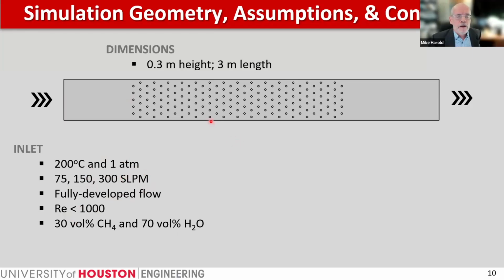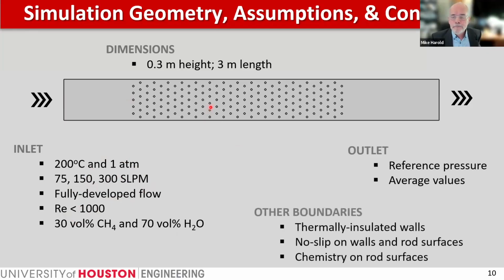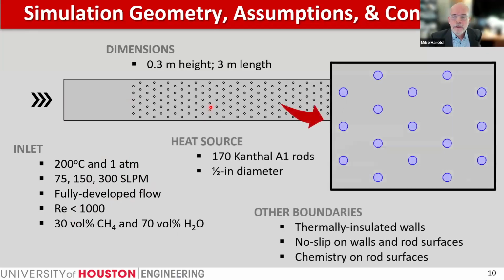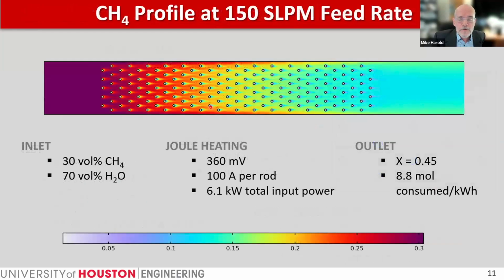This is a two-dimensional reactor where the catalyst rods are coming out at us from the screen here. So these are 170 Kanthal rods that are half an inch in diameter and coated with nominally 20 microns or so of nickel supported catalyst. We put all that into the reactor and simulate away, and I'll show you some results.